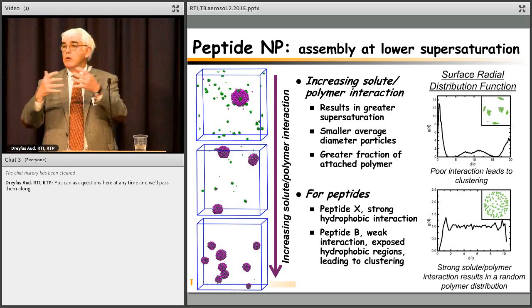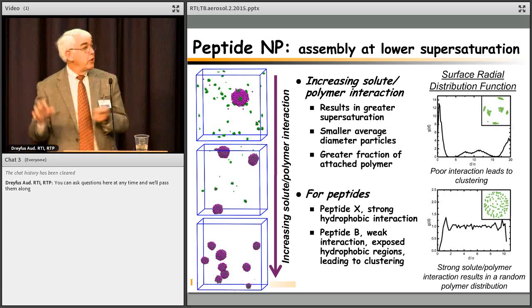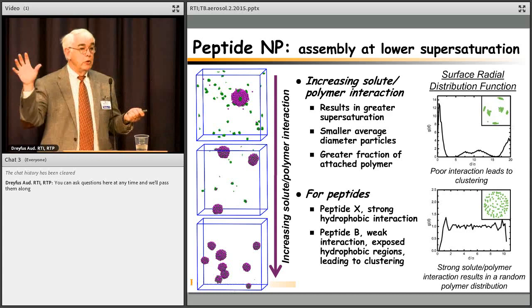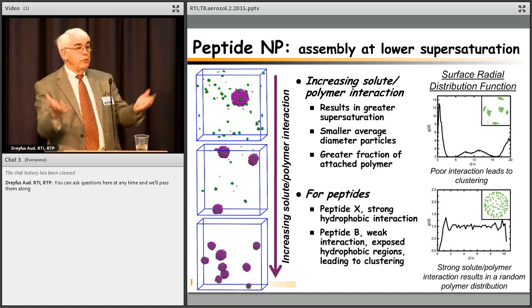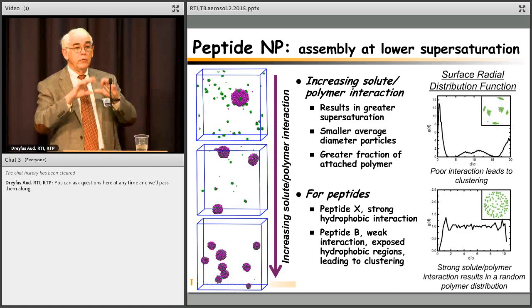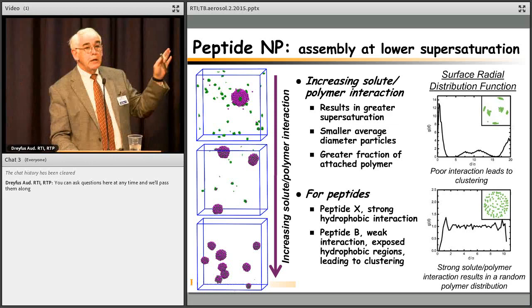And so this 1 micron size was the size at which you aggregate these, until now on these bigger particles, because of surface to volume, that is, I have less surface area per volume, so I've aggregated lots of small things. I actually have less surface area here than individually those particles had. So I concentrate these islands on the surface till they're close packed, and then that stops aggregation. Okay, so this tells us something interesting about anchoring energies and how we want to engineer that for these nanoparticles.